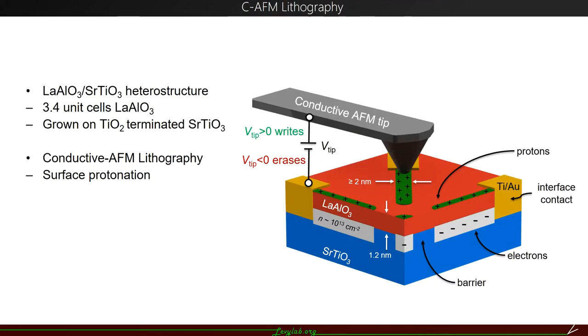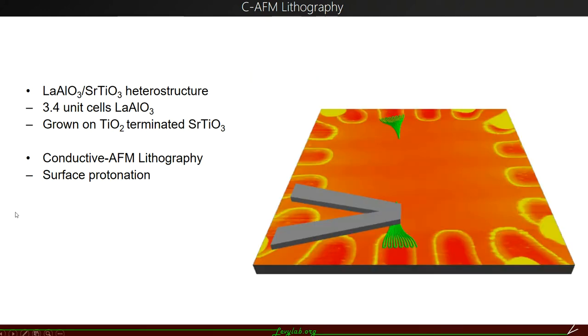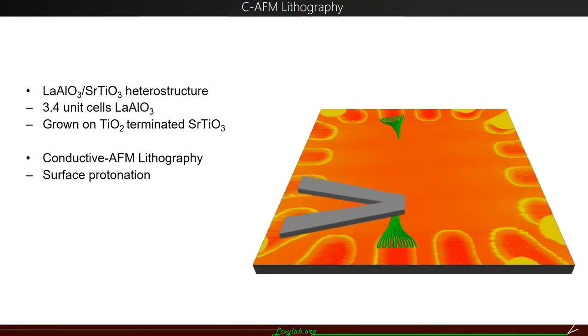More interestingly, with the conductive c-AFM lithography technique invented by our group, we are able to write nanostructures at the LAO-STO interface. This animation will demonstrate an example of the writing and erasing process. First of all, we apply a positive voltage on the AFM tip and write two triangular shaped patterns, which we call virtual electrodes. Those will help to form robust electrical contact to the oxide interface.